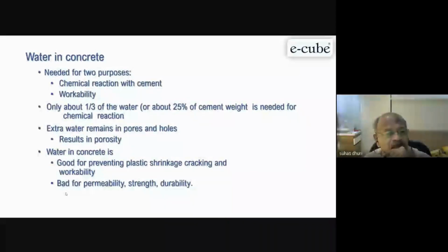Now, additional water, when you are working at site, we add water at maybe 0.4, 0.45, 0.5, those ratios. So we are adding almost double the water. Then what happens to the water which is not taking part in the reaction? That remains in pores or air bubbles in the hardened concrete, and that results in very porous concrete. So porosity is very high, permeability is very high, and you will have very bad durability and also strength. Some amount of water is good against plastic shrinkage cracking; when we discuss fresh properties, we'll discuss this. That's why we always say water has to be optimum.